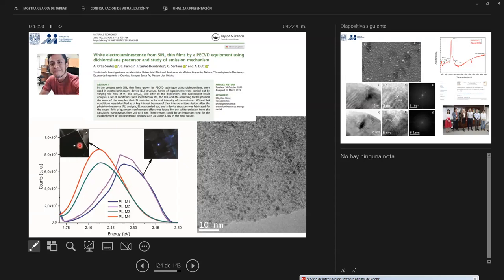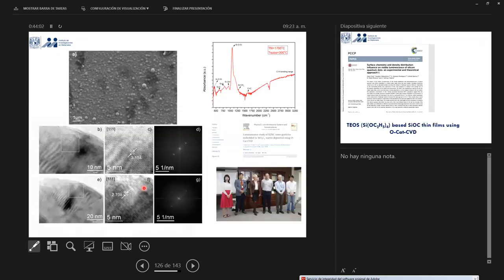In one case, we have a white color. In the other case, we have blue color. So we can control the morphological aspects of these silicon thin films. And finally, we can control the emission. Also, we are doing some work with Dr. Kita and Dr. Asahi in Japan, where we are trying to find the complete mechanism. We are trying to find how these silicon quantum dots are emitting, because there are different mechanisms again. These are quantum confinement effect, hydrogen defects, oxygen defects, NBOHC defects, self-trapped exciton defects. There are multiple kinds of levels.